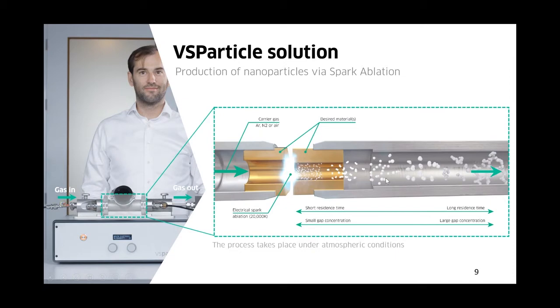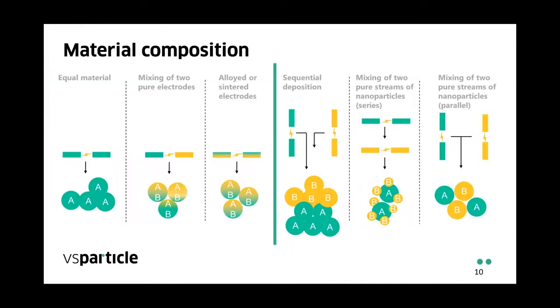What's really unique about this technique is that we can readily vary the average particle size by varying the residence time of the ablated material within the reactor head. By increasing the gas flow, you shorten the residence time, leading to smaller nanoparticles, and vice versa. A lower gas flow increases the residence time within the reactor head, leading to more aggregation and therefore larger particles.